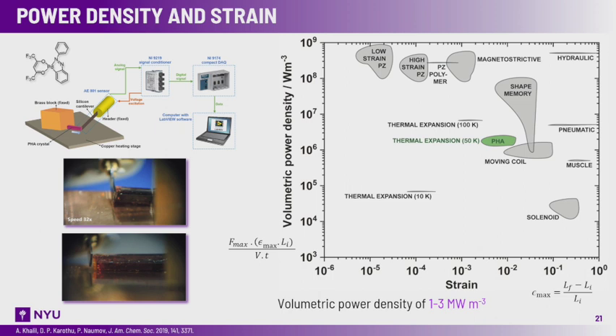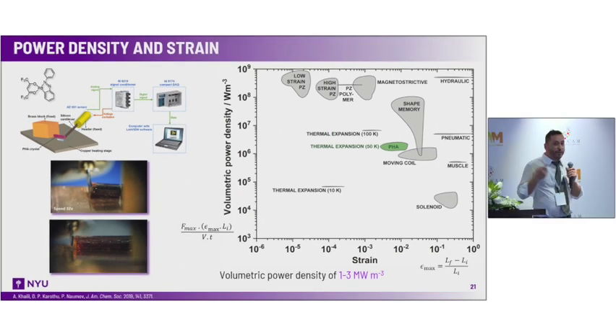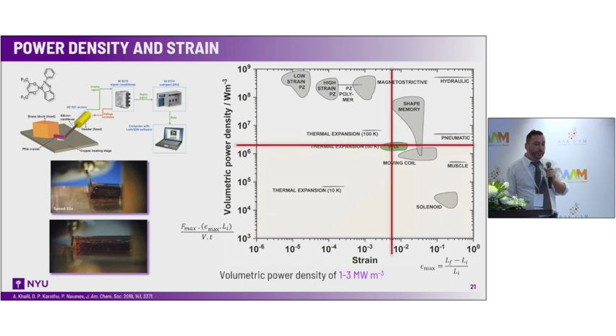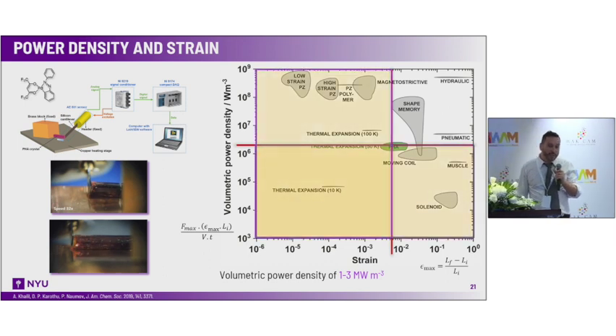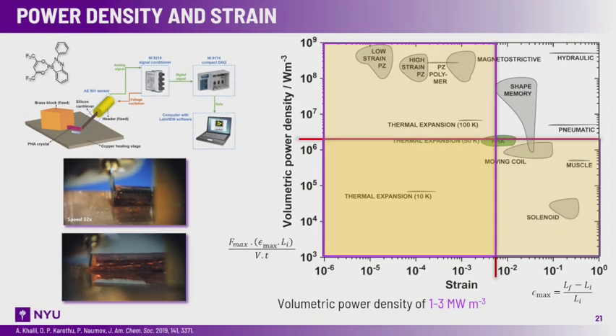So how do we quantify these materials or the force they can exert? Our way is to use a very sensitive force sensor that we attach to the crystal, and then we subject them to heating, and we measure the force directly. Based on this, we can calculate the volumetric power density. You can see from this plot that they can compete with other more common materials such as moving coils, solenoids, and so on. And they come even closer to some MEMS devices.